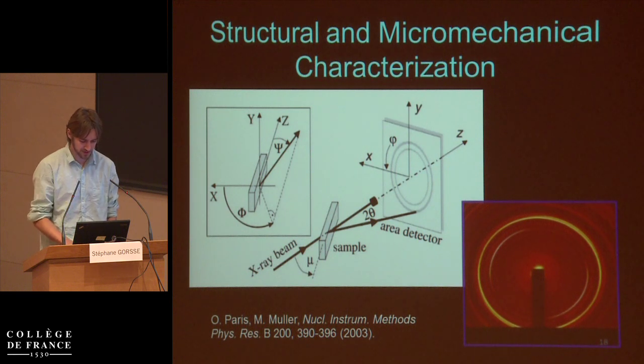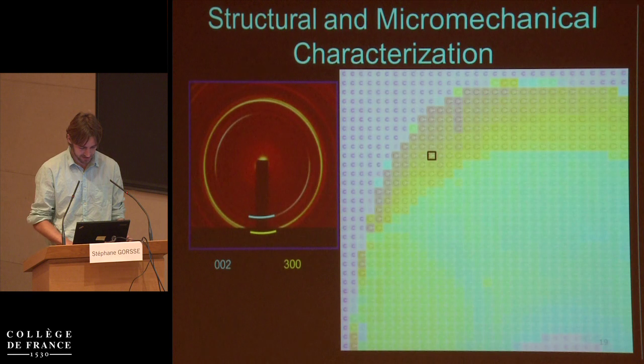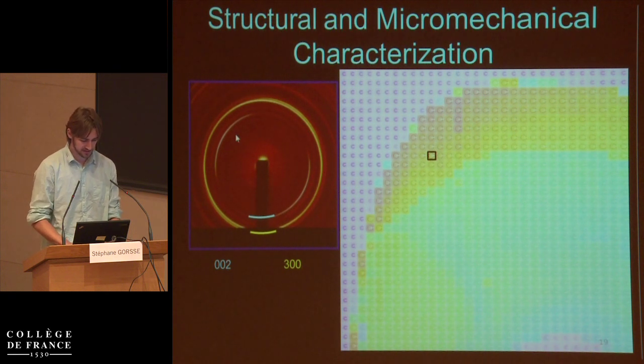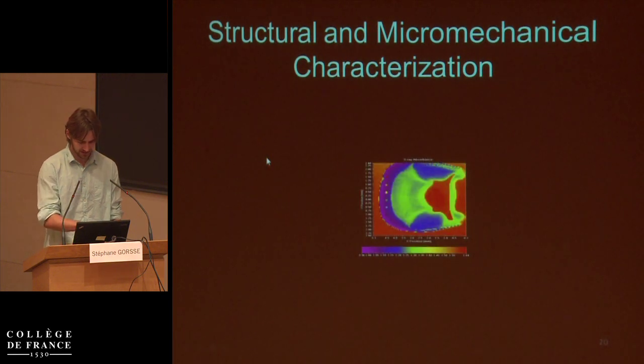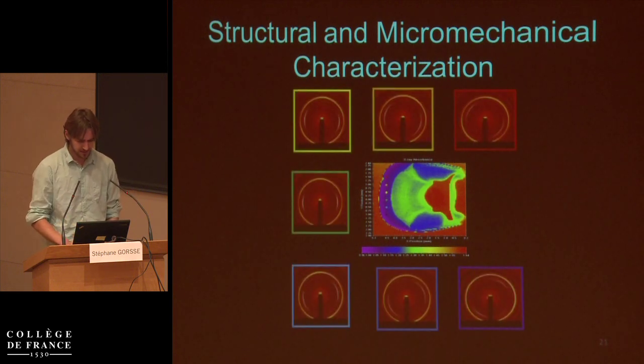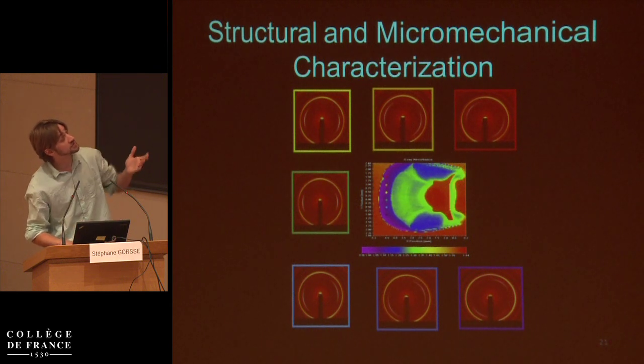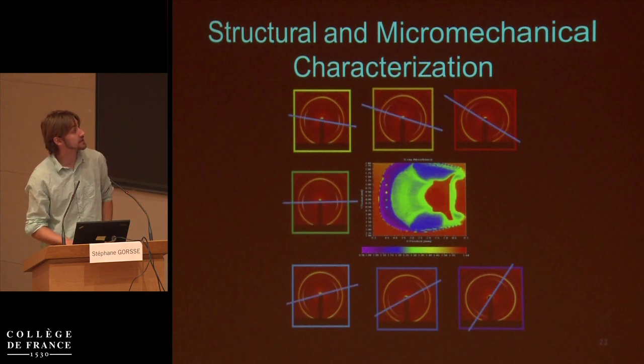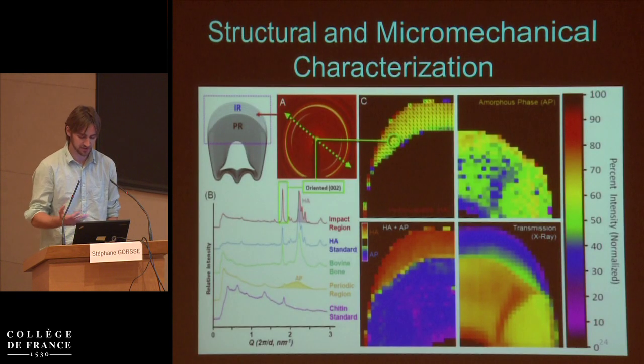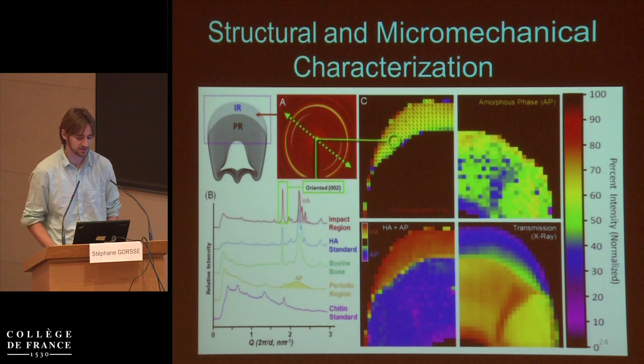So the characterization begins with some synchrotron. We took a large array of diffractograms, and this little black box here is one diffractogram. And you can see that the 002 axis is aligned. So if I take a collection of points, you can see down the center of this hard exterior. And then I could take those color-coded borders and arrange them around in a dais, and you'll notice that the 002 axis is changing its orientation as we move around in this dais. And then if I map those to the locations they were taken, you can see it's always orthogonal to the surface.